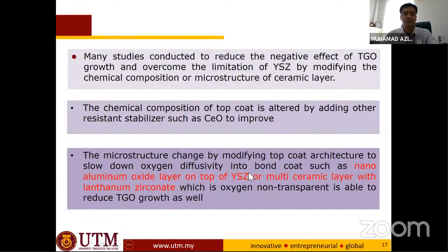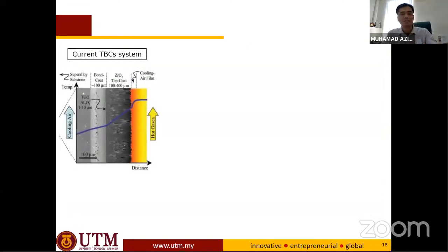The microstructure is changed by modifying the top coat architecture. For example, in this research, I use another layer on top of the YSZ, because YSZ has a temperature limitation of until 1200, okay? So we can have the ceramic on it. So this is the current TBC system. What do we have? We have the metallic coating, which is the bond coat. This is your substrate. And this is the zirconia, or YSZ.